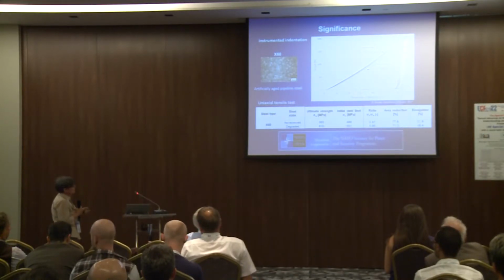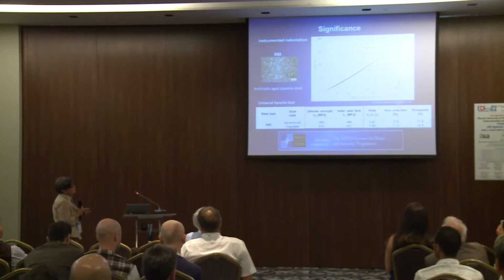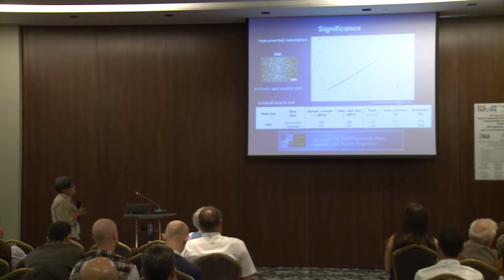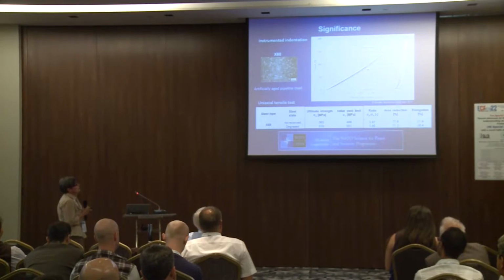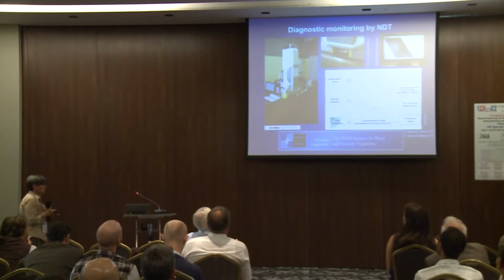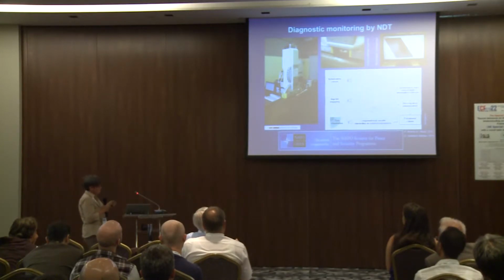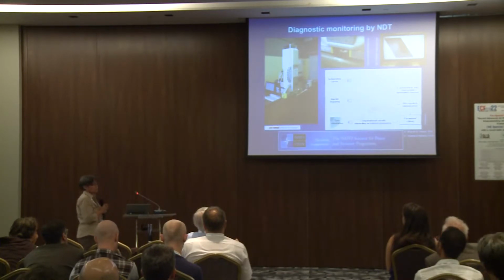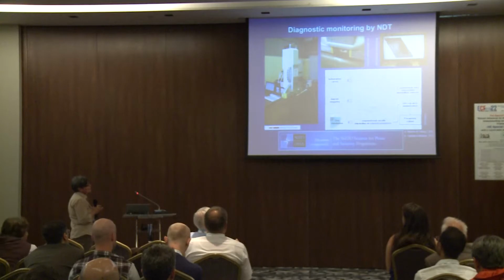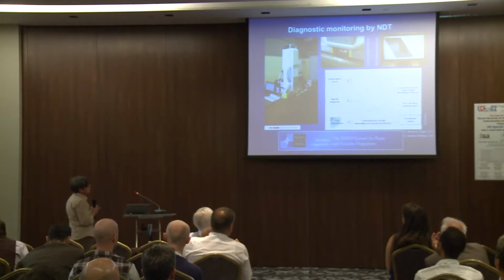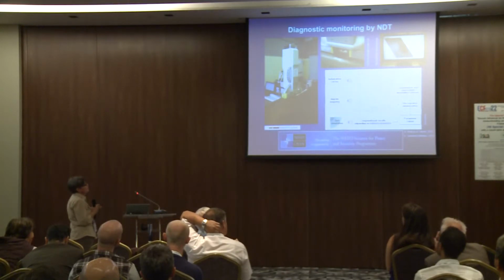And as I was saying, there are two families of curves which are clearly distinct, which concern the as received and the degraded conditions. So the indentation test is not able to reveal change in rupture elongation, but reflects clearly other material properties like strength and yield limits. And it has been proven in former studies, which were also carried out together with colleagues from Professor Nikki Forching's group, that you can rely on a system like this one, where there is one indenter, which is a tool which can be applied directly on the pipe on site, and you can recover directly, without cutting any kind of specimen, the so-called indentation curves that we have seen already in the former slide.